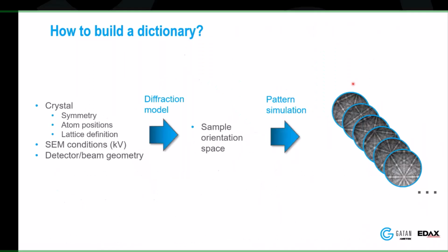And this is kind of getting to the main thing here: you have to build the dictionary, which is one of the issues. So over here we have our crystal information, our lattice parameters, where everything is, your SEM conditions, your beam geometry. Then you run through a model, and you sample your model in orientation space. Then you build the dictionary in the end, and you have this huge dictionary of all these different patterns.